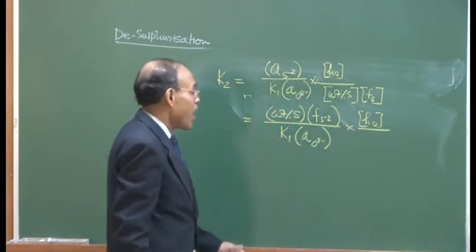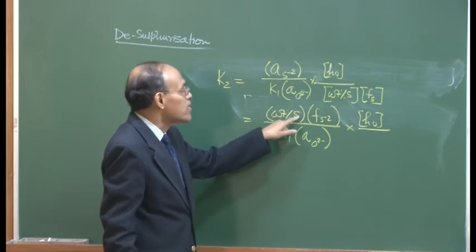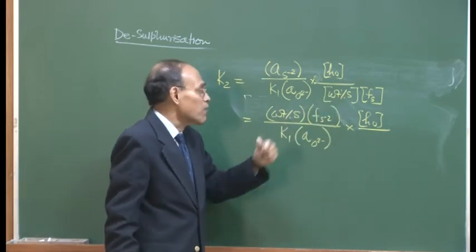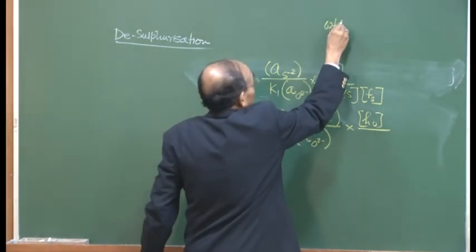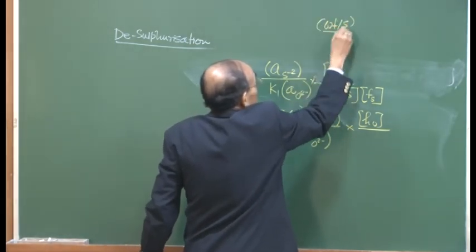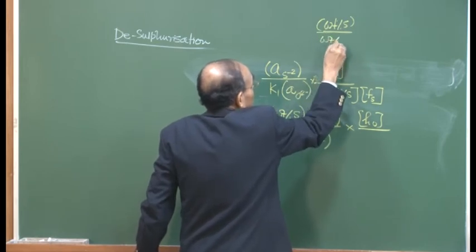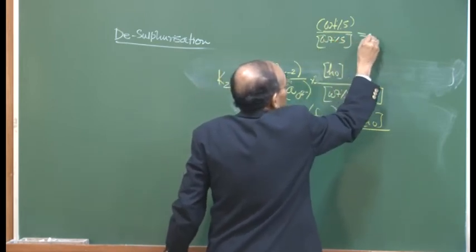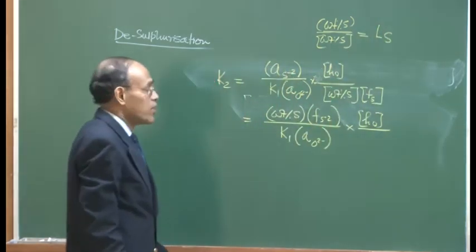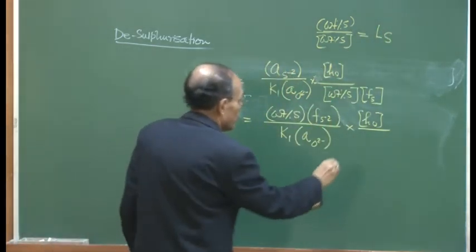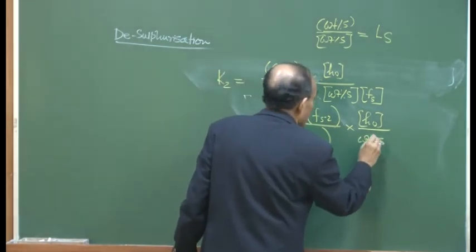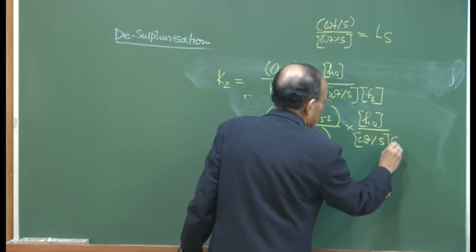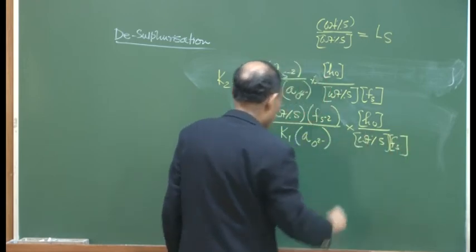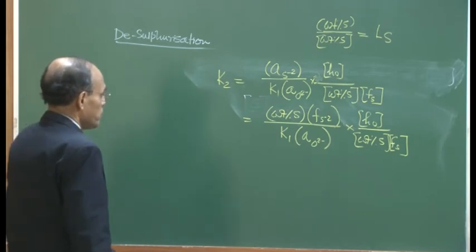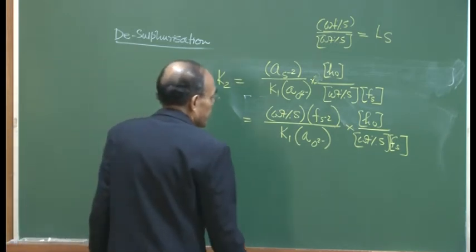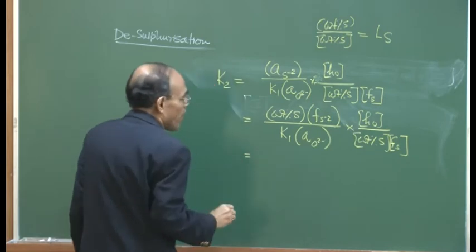What am I trying to do? I am trying to find out a ratio of weight percentage sulfur in the slag to weight percentage sulfur in the metal, which represents the efficiency of sulfur removal, actually the thermodynamic efficiency of sulfur removal, which is also called the sulfur partition coefficient, and is represented by the notation LS. And then we have weight percentage sulfur into activity of sulfur in the metal. So we get here this parameter now.